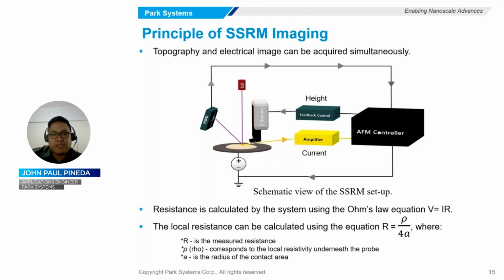To acquire electrical data, a DC bias is applied. DC bias current is applied between the tip and the sample. So here, the conductive tip acts as an electrode, and the direct current passes through it. Generally, this current has a very small magnitude. Therefore, a logarithmic current amplifier is used to amplify the current signal before it is processed into an image.